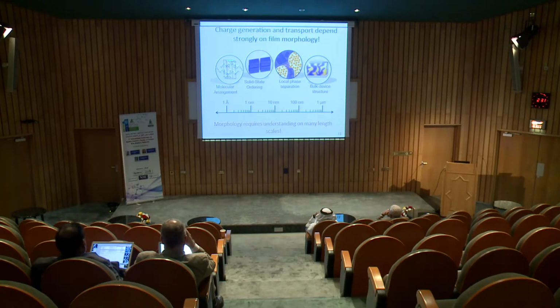As you can see, in this type of solar cell device, the performance depends strongly on the film morphology. So what do I mean by film morphology? You start with molecules and how they arrange at the molecular level, and they self-assemble to form a solid state with nanoscale features. Then when you have the donor mixing with the acceptor, they phase separate and form nanoscale domains, and they form a bulk heterojunction with percolation pathways to transport charge.